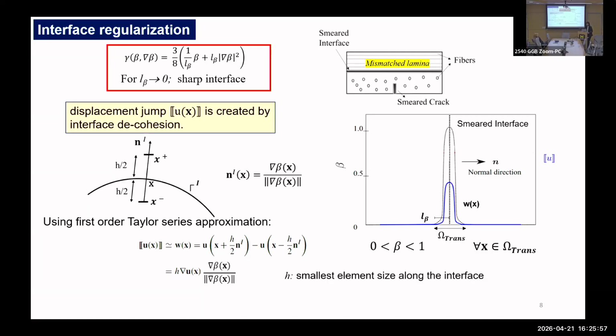That automatically comes because, remember, we smoothened the interface field also, through the introduction of the beta parameter. We need a smooth approximation for beta anyway, which tells us that we need to resolve our mesh fine enough so that this jump approximation remains accurate. So now we have a smeared crack, a smeared interface, and the jump across this interface is also smoothened out. There is no sharp discontinuity in the entire domain at all.